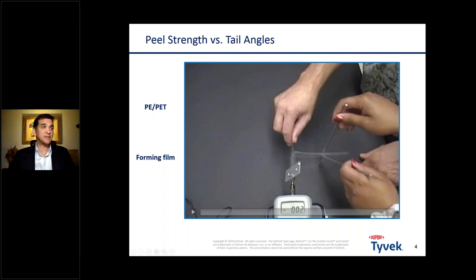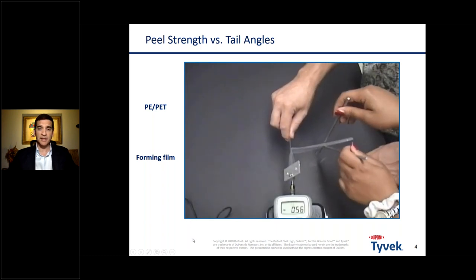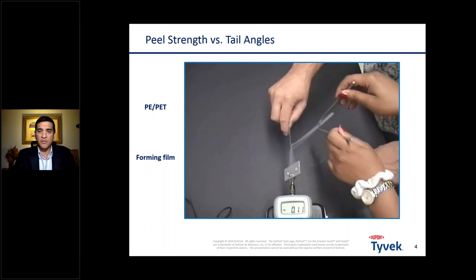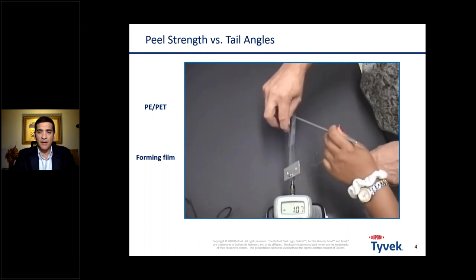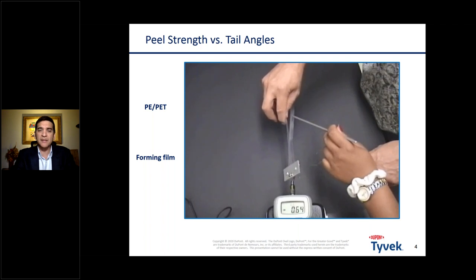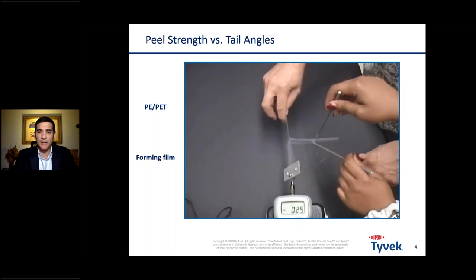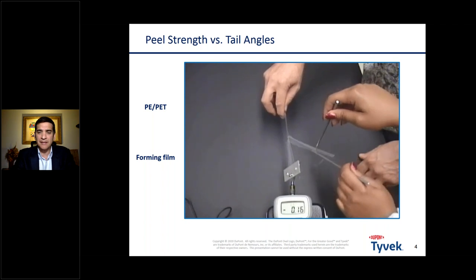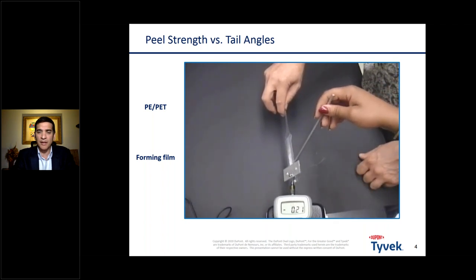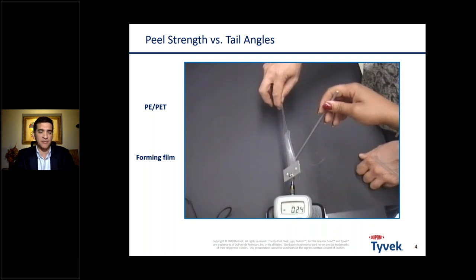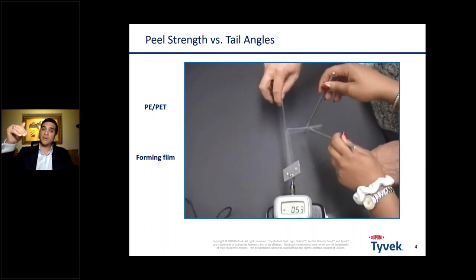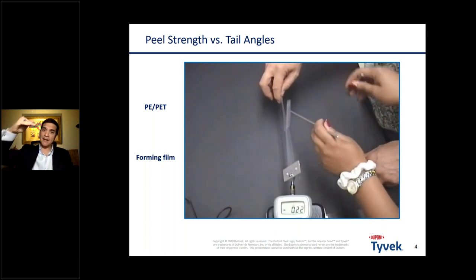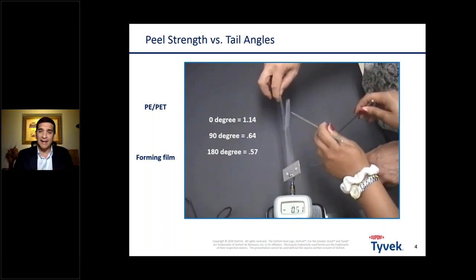So as you can see here, if you give me a second to start up the video, we start off somewhere in that 0.64 range at 90 degrees. Now when we go all the way to the top and pull, we're going to see a range of 1.14, which was the high point, and then back to 90, and then back over here to 180 at 0.57, or somewhere in that neighborhood, right? All we're doing is changing the angle of the pull, and we are getting radically different numbers, right? So from 0 degrees, we got 1.14. At 90, we got 0.64, and at 180, we got 0.57.